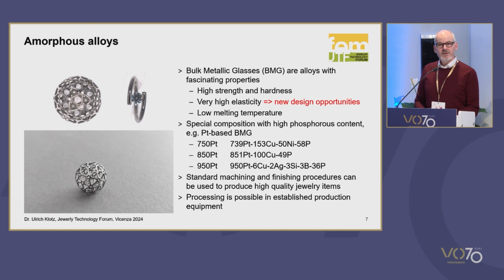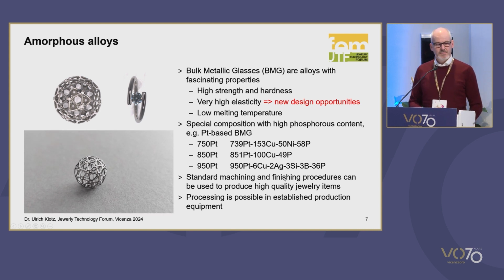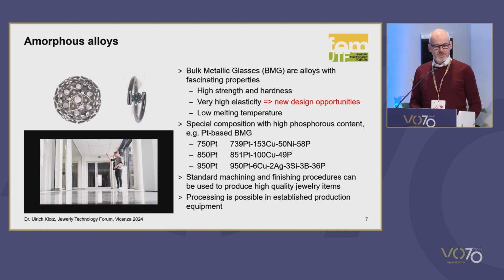Then here is a little movie. The lower image, maybe you can play this, please. So this is something I presented last year. This is a bulk metallic glass, a platinum-based alloy, which has extremely high elasticity. So you're seeing my colleague Lisa, she's dropping this ball, and it bounces back like a rubber ball. And that's because of the very high elasticity of these alloys, and that is very different from conventional alloys. So these alloys form at very special and specific compositions, and therefore it's also important to find out these compositions. And just by melting alloy after alloy, this is very time-consuming and also money-consuming, so we need screening techniques to find such compositions.